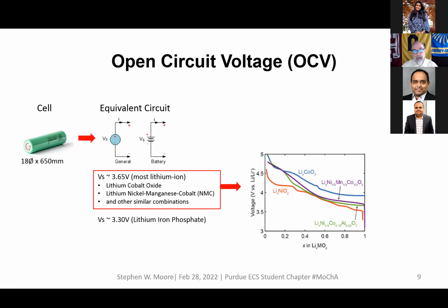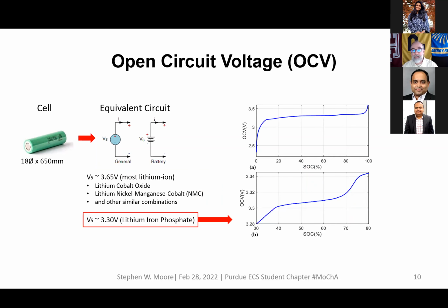They move with how much lithium is in the cathode and in the graphite. Basically, as the lithium moves from the cathode to the anode, the battery discharges and the voltage goes down proportionally to the amount of lithium that's being moved in the battery. And you can see all the different types of cobalt: lithium cobalt, lithium nickel manganese cobalt, lithium nickel cobalt aluminum, and they all have very individual curves. So it's not so simple to just use a voltage model. And then lithium iron phosphate has a flatter curve that averages somewhere around 3.3 volts.